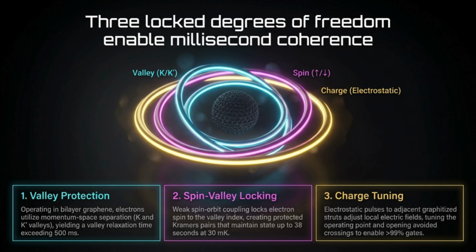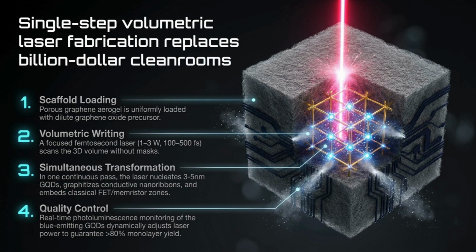Which sounds impossible, but the critical mechanism that makes this feasible without a mask is the real-time, closed-loop feedback. Right. As the femtosecond laser ablates the carbon to form the quantum dots, the plasma plume and the dots themselves emit a specific blue photoluminescence. By catching that luminescent signature with a spectrometer in real time, the control software can analyze the precise size and band gap of the quantum dot as it is being formed. So if the dot is growing too large, say trending towards 6 nanometers instead of 4, the system instantly throttles the laser power. This closed-loop photoluminescence monitoring guarantees the exact uniformity required to maintain the specific spin valley parameters across the lattice.